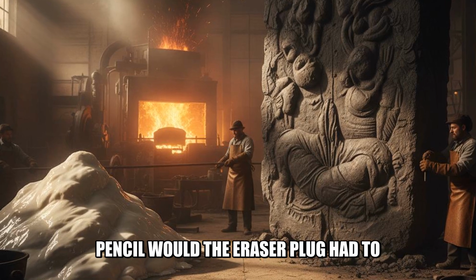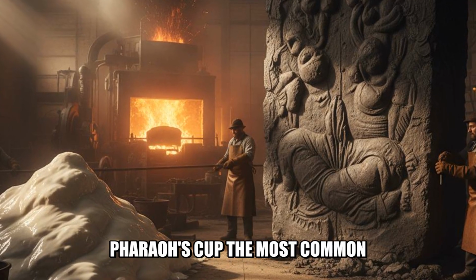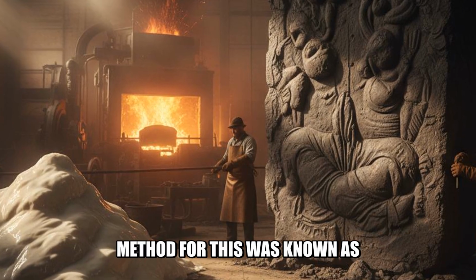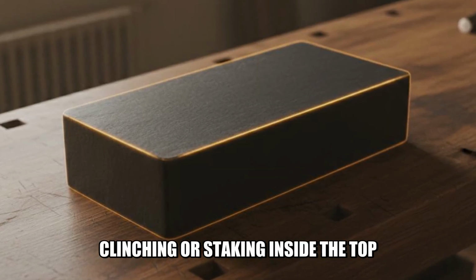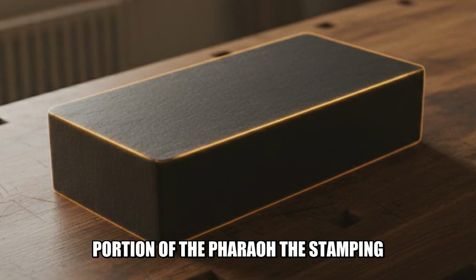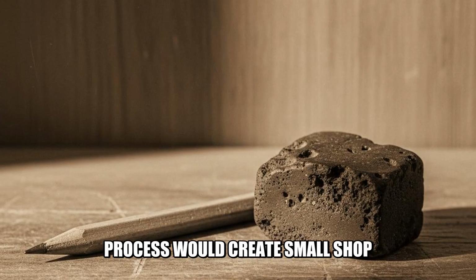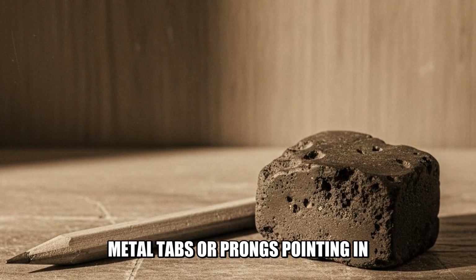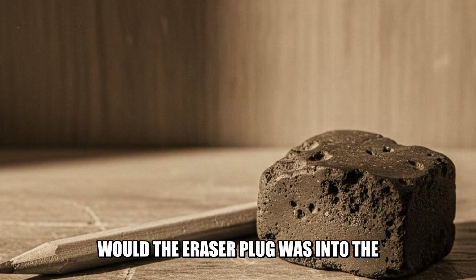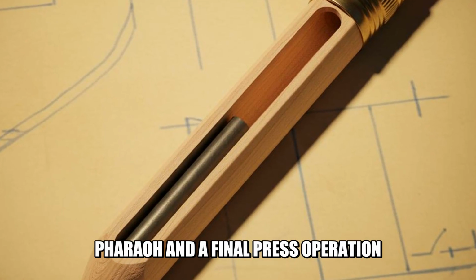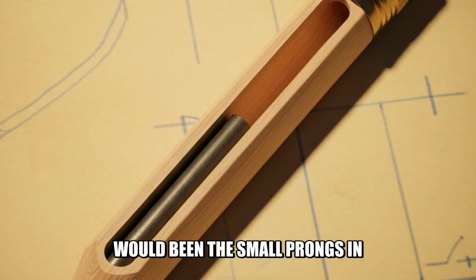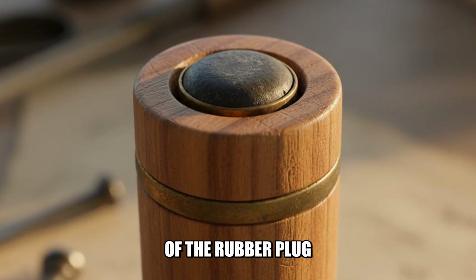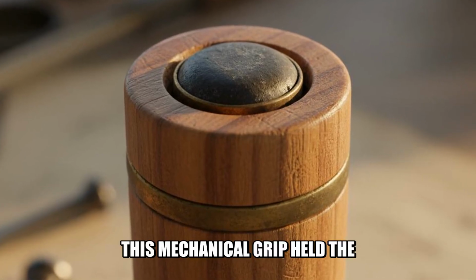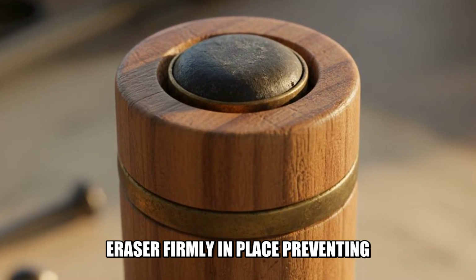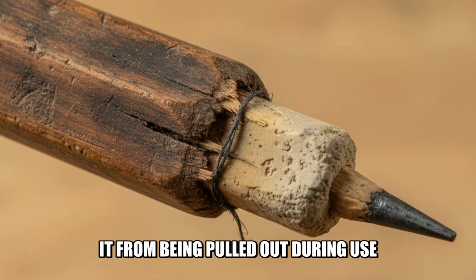After the ferrule was crimped to the pencil wood, the eraser plug had to be inserted and secured within the ferrule's cup. The most common method for this was known as clinching or staking. Inside the top portion of the ferrule, the stamping process would create small, sharp metal tabs, or prongs, pointing inward. The eraser plug was forced into the ferrule, and a final press operation would bend these small prongs inward, causing them to dig into the sides of the rubber plug. This mechanical grip held the eraser firmly in place, preventing it from being pulled out during use.